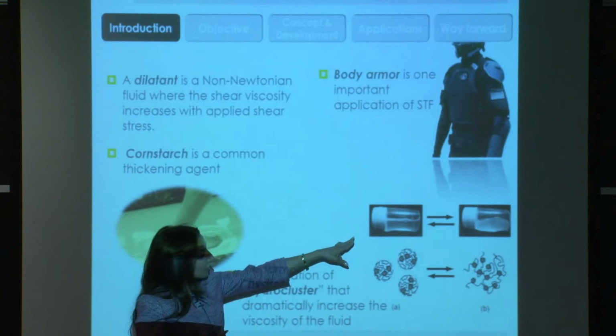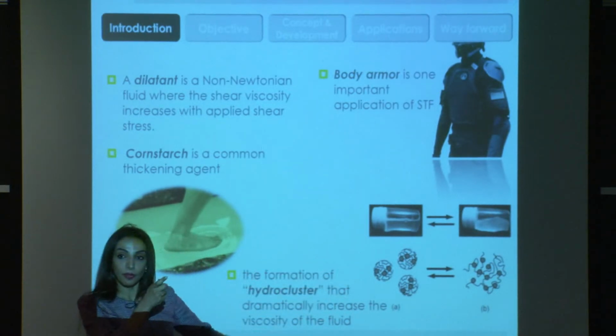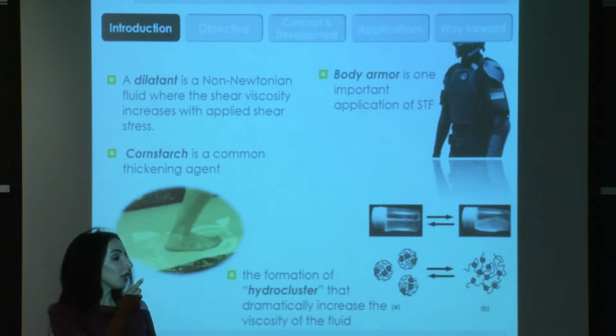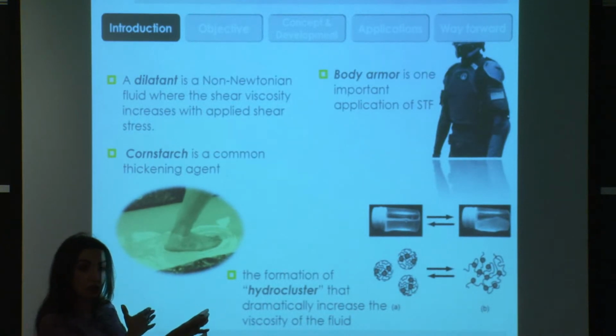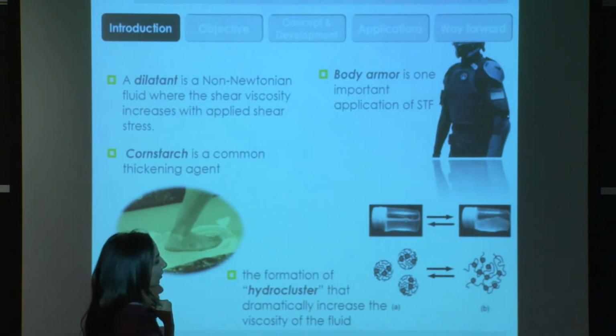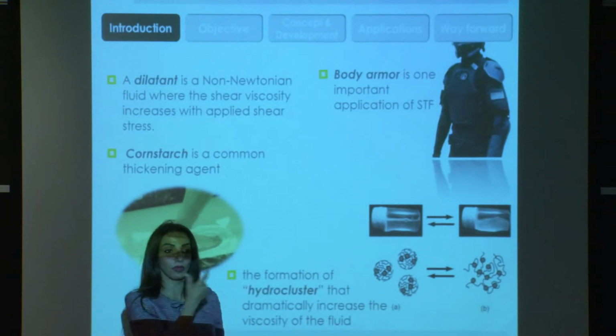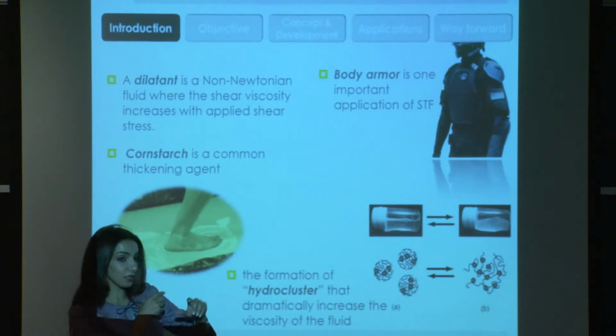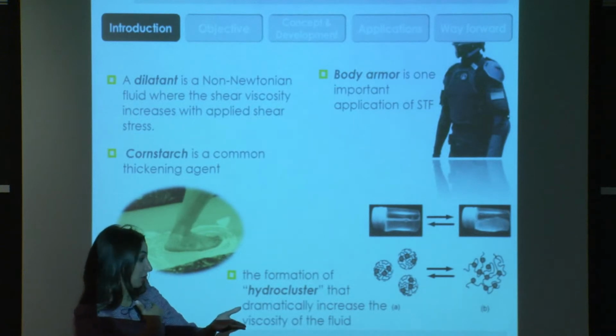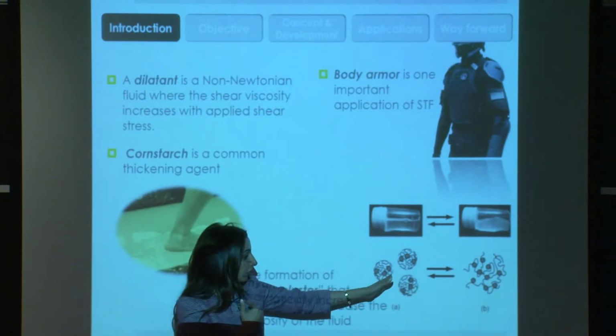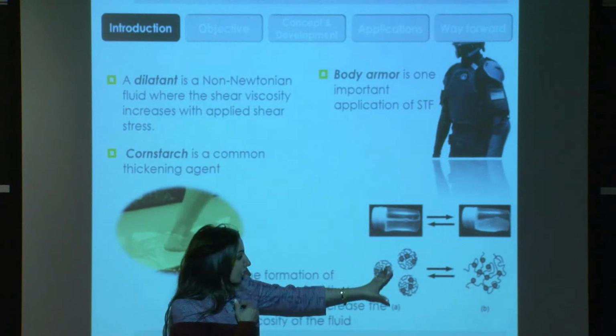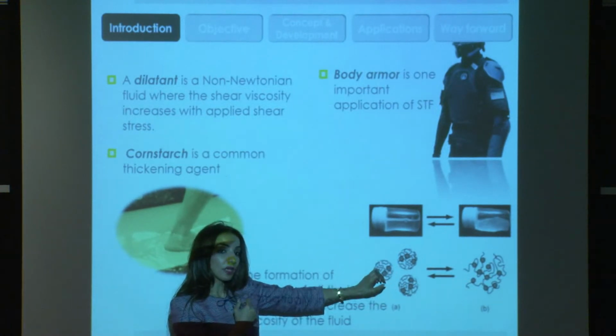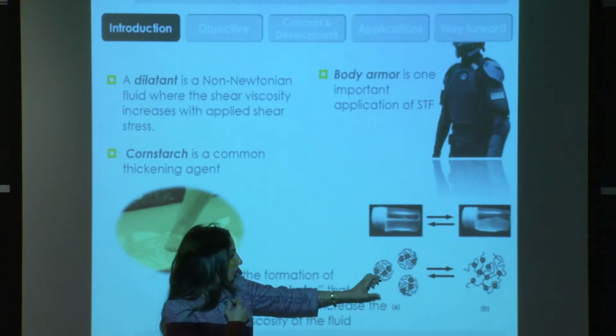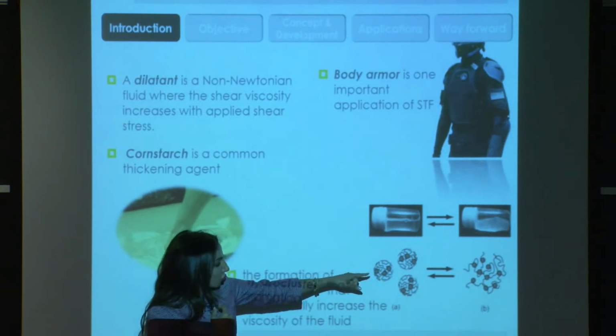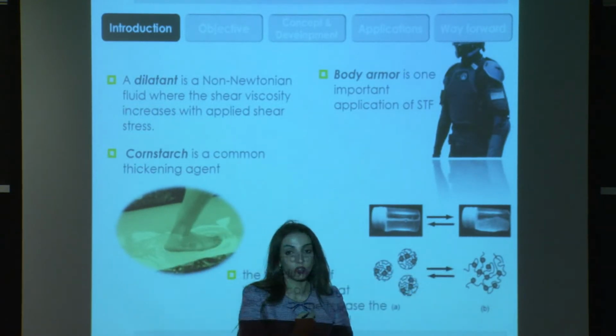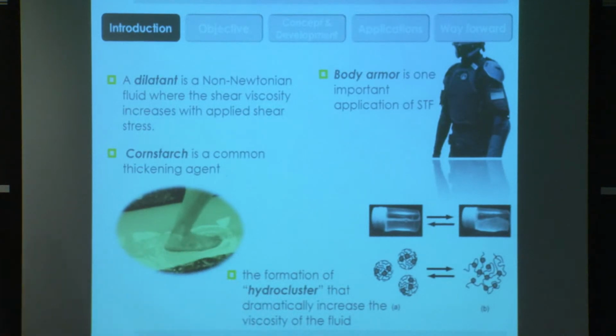So as you can see here on the left side, this is the shear thickening sample in normal situation. As you can see, it's a liquid, and the one on the right, after shaking the same sample in horizontal direction, is transformed to a gel, and this is the corresponding structure model. As you can see, it transfers from separate clusters to a three-dimensional network.